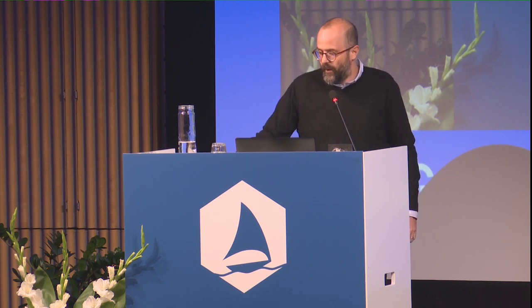If I imagine doing this with a system in which the graphene is aligned on both sides with boron nitride, there I start off with a gap that's about 70 meV, and I would expect that I would get the same response. So you might be able to get to 150 meV or so in this system. That could be interesting to some of you because I think that it starts to become technologically relevant by some metric. Okay.